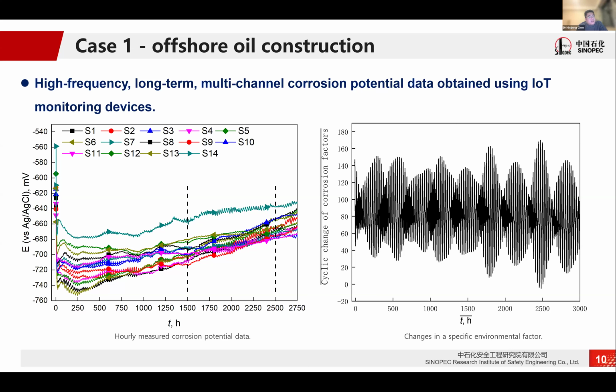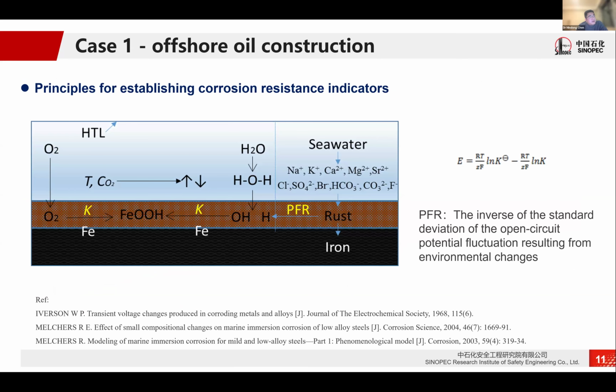At the same time, we also have the data of cyclical environmental factors so that we can analyze the internal relationship between the two data. We analyzed the fluctuation characteristics of the measured results and established an evaluation index of corrosion resistance. This index is different from the corrosion rate, but it can also reflect a certain corrosion resistance factor in the corrosion process. When potential fluctuation occurs, the reaction equilibrium of the metal in the environment shifts.